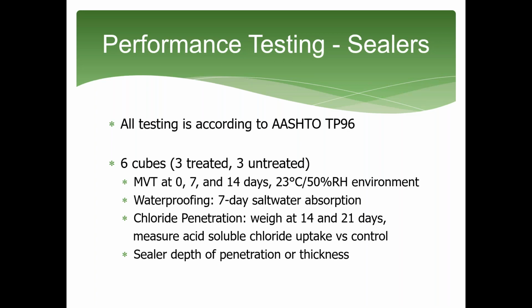The cubes are then split in half. Half is tested for chloride according to AASHTO T260 at 4 sampling depths, and half is tested for sealer penetration or thickness. Penetration depth involves immersing the sample in a solution of dye, and the coating thickness can be determined by ASTM D6132 or microscopic examination.